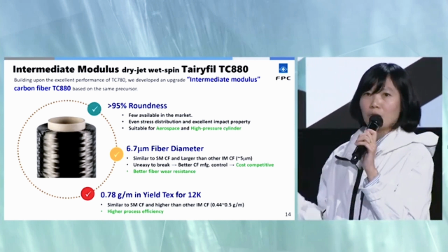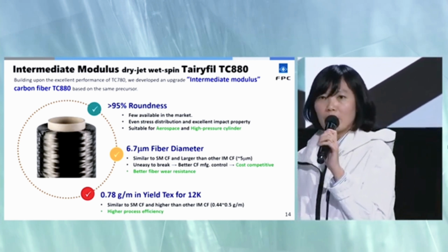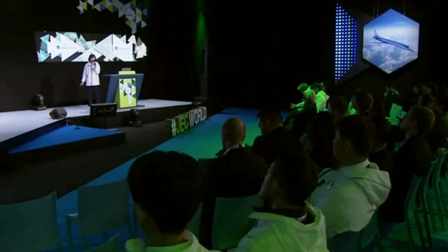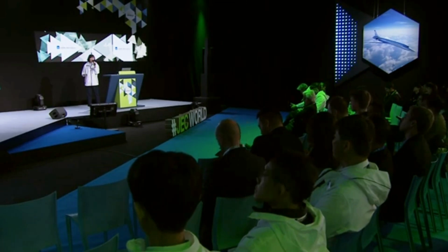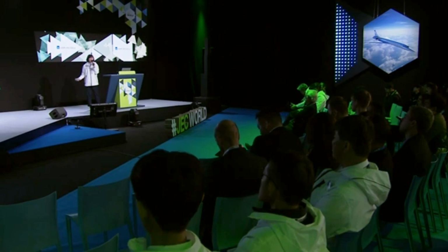And different from other intermediate modulus fibers, our fiber exhibits larger diameter, which helps the fiber be less likely to break. So it will be easy for our manufacturing process control, so it's a cost competitive fiber. It also shows better fiber wear resistance because it is less likely to break with the larger diameter. And it also shows a higher yield, so it shows a higher process efficiency.